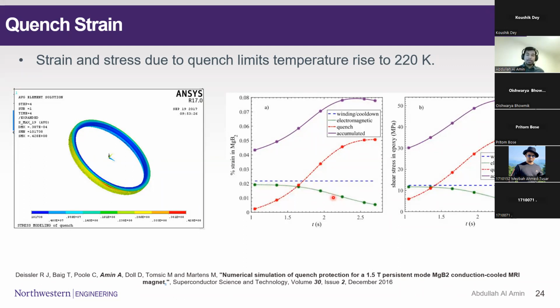As time progresses, when there is a quench, the magnet is partly resistive, and we do not want the electricity to pass through at exactly the same amount. So when we detect the quench, we have a detection system and a protection system, which eventually drains out all the electricity. That's why this green plot is going down. When we combine all of these and add them together, we get this purple line, which gives us the exact state of the strain. We can see that the strain does not go beyond 0.08% when we have this protection system on. So that means the magnet is being saved.